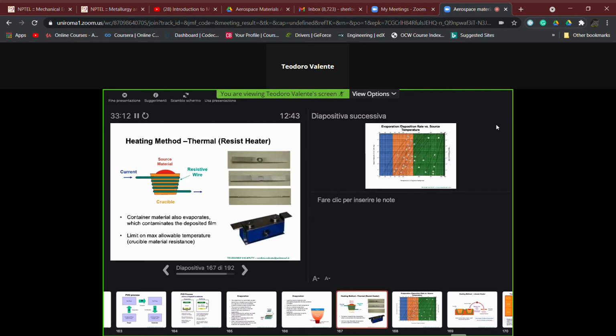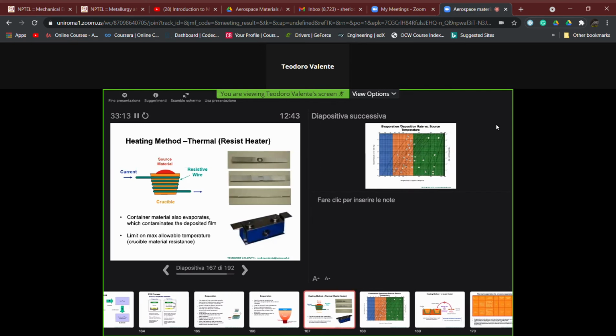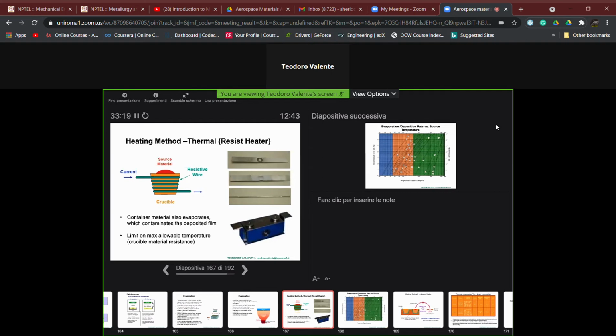If we want to discuss the principles, here you have some examples. We can have heating by current by using a resistive wire, that is, as I said to you, by relying on the Joule effect. But due to this simplicity, we do have some limitations. One limitation is that in order to have a suitable value of partial pressure of the materials coming out from the source by sublimation, we need to use, generally with this simple configuration, low melting point